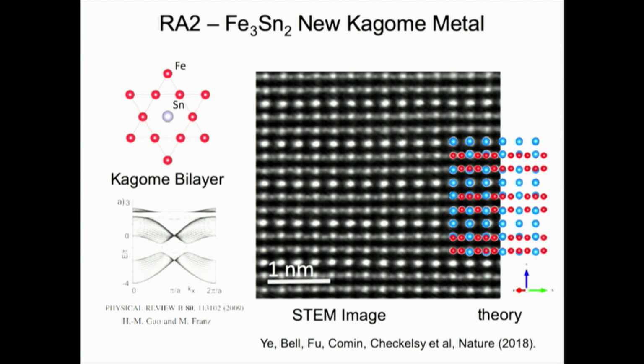But then we have an excellent set of high-resolution transmission electron microscopes at Harvard. And so we put it in the STEM and then take a look. And you can see the crystal structure directly. And so you can see the layers in here, and sort of two narrow ones with big atoms and small atoms, and a little bit of offset, and then in between others. And if you look at the theoretical crystal structure on the right, as shown here, it's sort of a direct overlap. You can just put one on top of the other. And at that point, they became quite happy and realized that things were working.